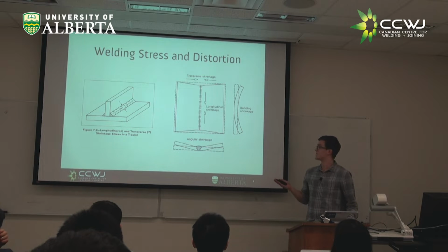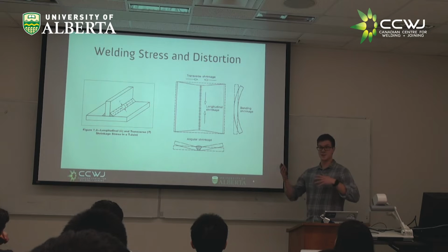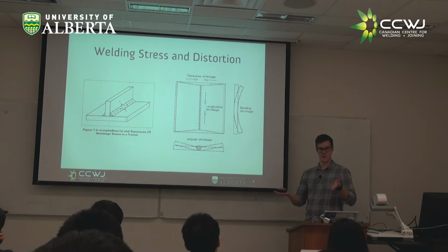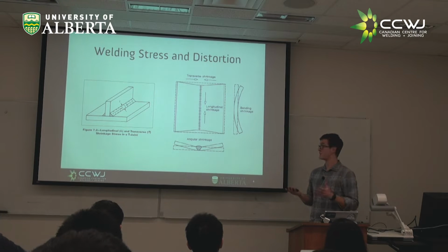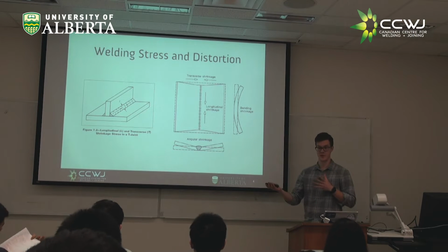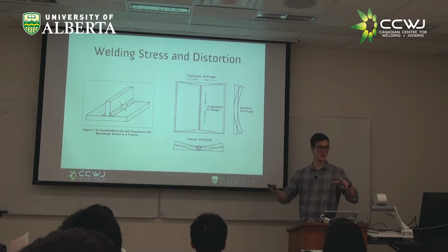And it's true that in some cases, you might have high distortion and low stress, or high stress and low distortion. But the reality is typically somewhere in between. You're never going to have no distortion when you weld, unless you really, really clamp your part so it can't move at all. And you're typically never going to have no stress either. The reality is as you develop some amount of stress, your part's going to deform a little bit, distort, to try to redistribute that stress into the lowest stress state it can achieve, and you're going to have some distortion. And if you clamp it in some way, you might have more stress in one part because you've restricted it so it can't move. But if you let it freely contract or freely,